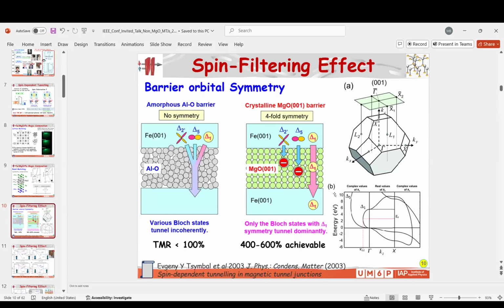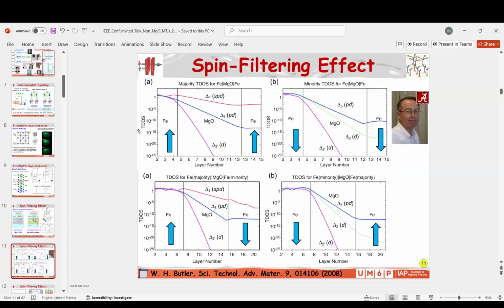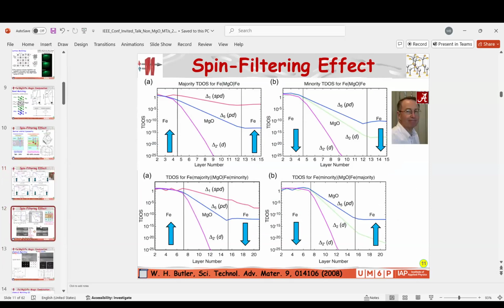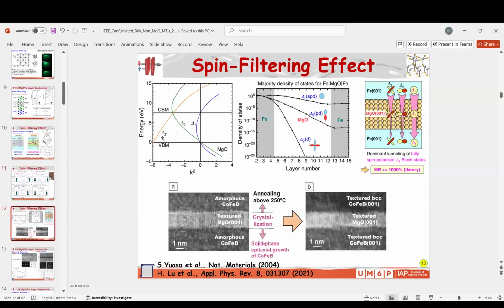In addition to this, the decay coefficient of delta 1 in MgO is smaller than the other orbitals, the other bands, delta 5 and delta 2. And this is very important. If we go through the spin filtering effects predicted by Butler in 2001, in the parallel states, we have a dominant delta 1. Once we go to anti-parallel, we get the decay, and by this process, we expect high TMR. I will go through a little bit faster.